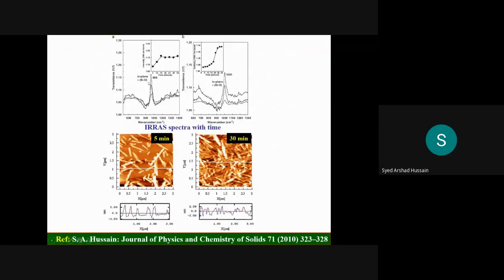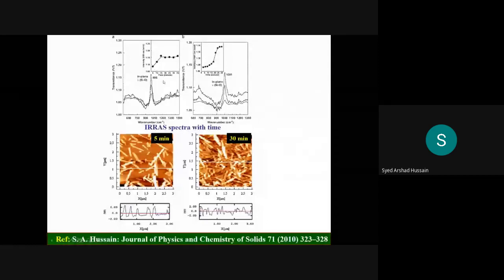You see, this is the vibration of the SiO band of this silicon tetrahedron when incorporated on the surface during this hybridization process. And you can see the plot of intensity with time. Initially, it increases, and after some time, it flattens. That means after some time, all the clay material has come up onto the surface and the interaction is complete. Then you can transfer your material onto the substrate for further application or investigations.